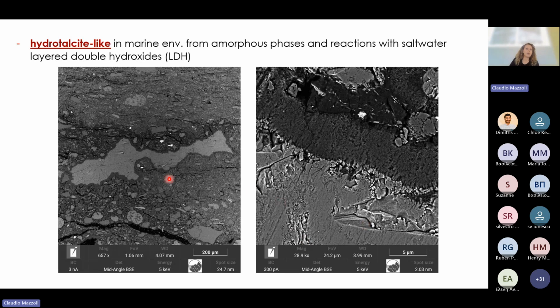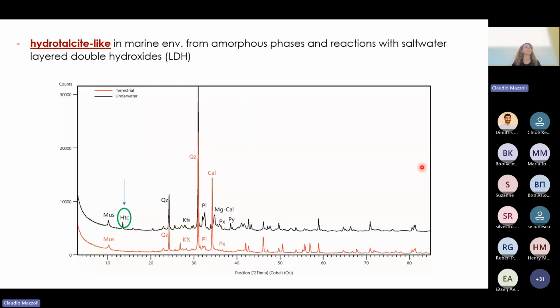In some cases, we recognize hydrotalcite also at the rim of porosity, but the pores were then filled by calcite. So this is the detail of this image, in which inside we have calcite and outside we have this darker rim formed of hydrotalcite. Obviously, under the scanning electron microscope, we can see the chemistry, and we have to couple this with diffraction data.